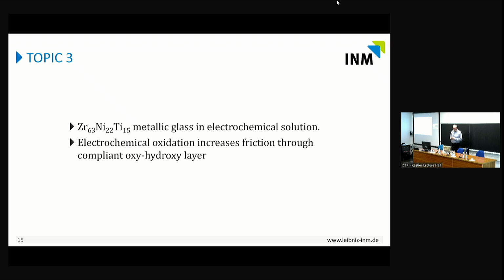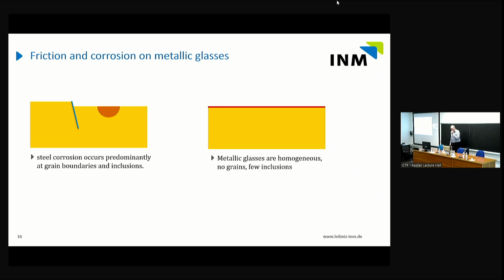He worked on metallic glasses in electrochemical solution, and we got interested in, can we switch friction on a metal by electrochemical switching, oxidation essentially? Now, originally I was very interested in doing electrochemical AFM on steel. It turns out that this is practically impossible, and the reason is the power of AFM is on the nanoscale. But electrochemistry on steel happens at grain boundaries and at inclusions. But these inclusions are never nanoscale. They just explode. It's a little bit like if you would take a profilometer and go to a volcano and try to image something. It's possible, but it's useless because you don't actually image the relevant things.